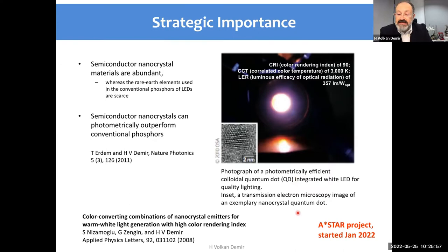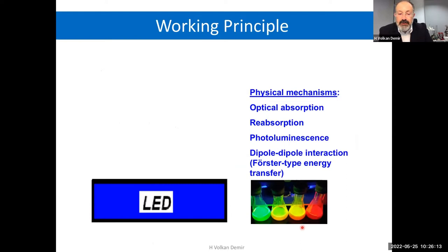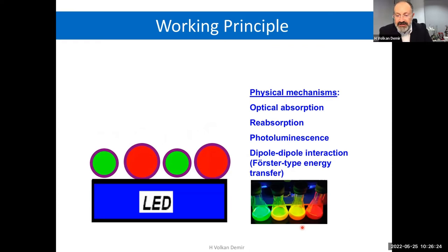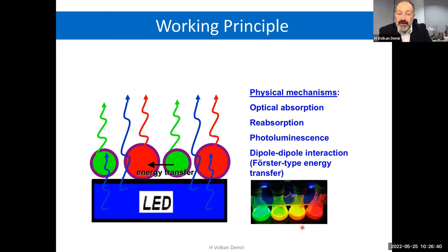And this quite recently turned into a large-scale project with our colleagues from A*STAR at NTU. So for the next 5 years, we have more work to do in this exciting direction. Just to look at how it works, it's actually quite simple. You could use this intimately on a direct LED platform, or you could do it in a remote configuration. In either case, you need to put together your color converters. They could be layered, or it could be all together, but you have to be careful in how you'd like to optically pump. And then you need to make sure the interactions in between are taken into account. Finally, you have to make sure the remaining blue along with the converted red and green actually provide you collectively the right white point along with the targeted photometric performance.